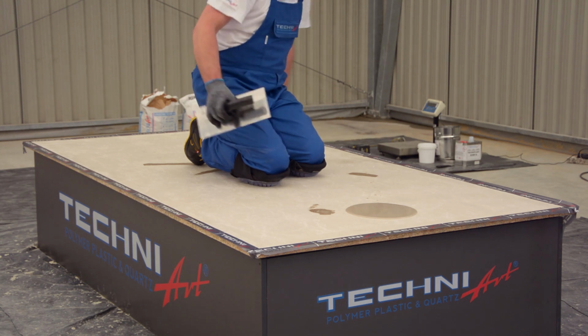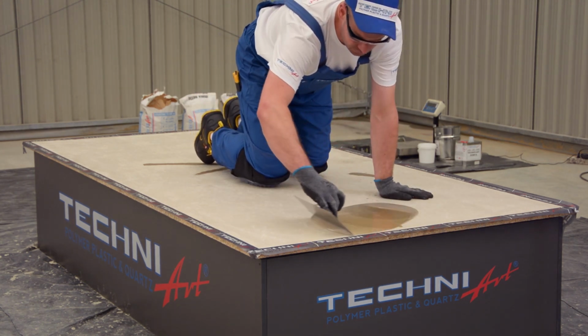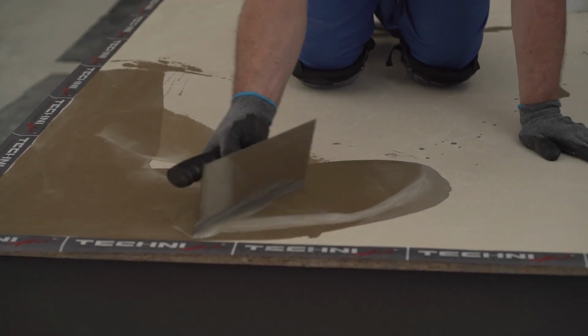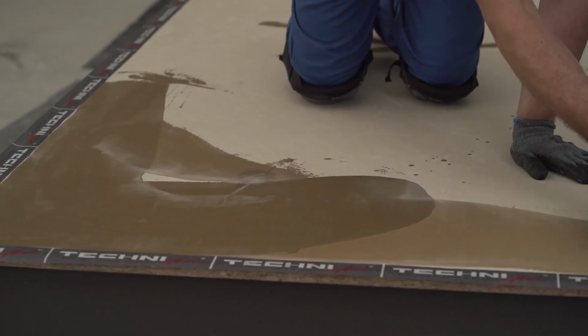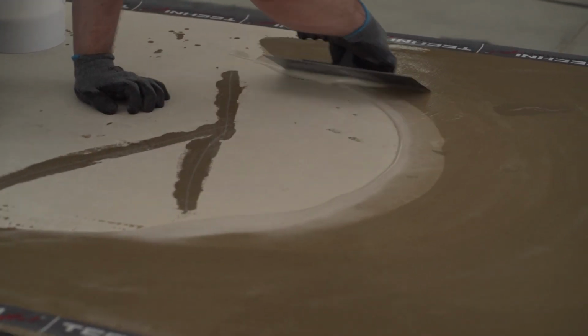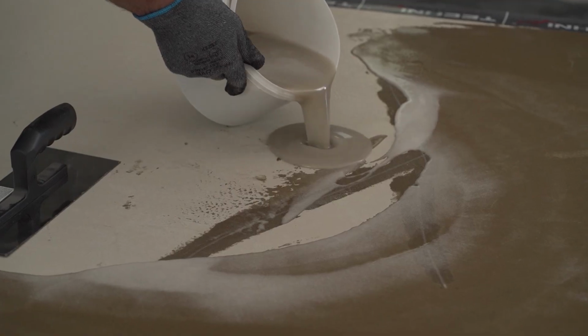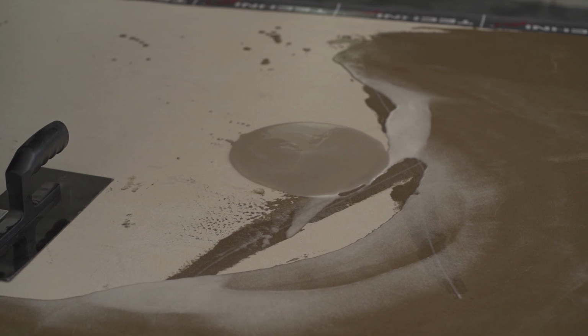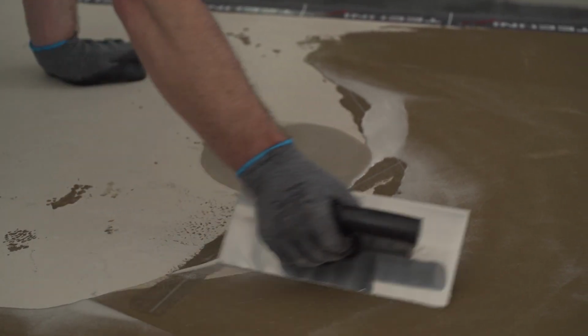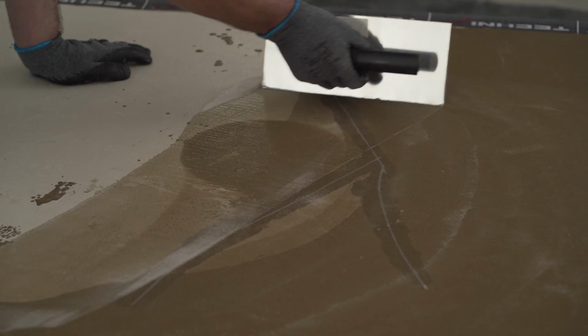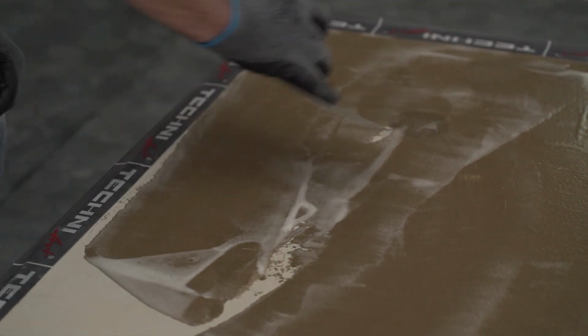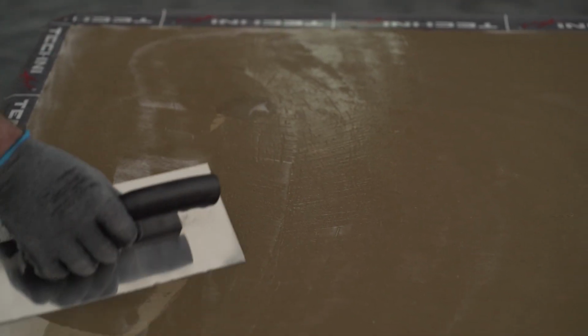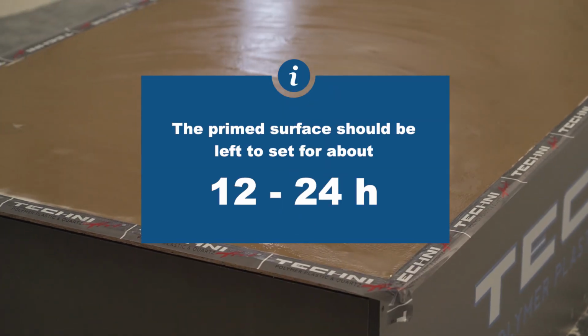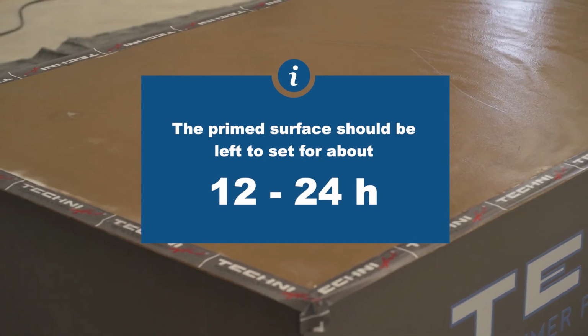The prepared mass should be evenly spread with a stainless steel trowel. Priming of category 1 and 2 substrate can be done by applying the resin without the addition of quartz sand using a resin roller. However, it should be remembered that the best effect is obtained with a putty primer. The primed surface should be left to set for about 12 to 24 hours.